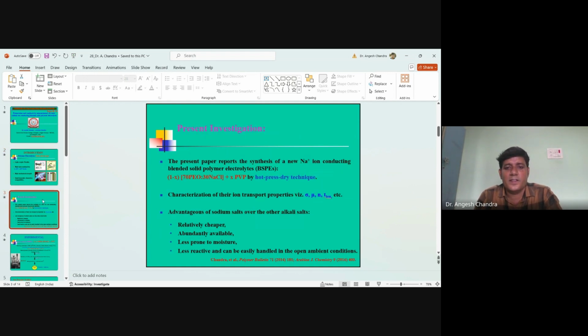Now in the present investigation, we have synthesized new sodium ion conducting blended solid polymer electrolytes, PEO, NaCl and PVP, and characterized their ion transport properties like conductivity sigma, ionic mobility mu, mobile ion concentration n, and ionic transference number t_ion. The advantage of sodium ion salts over other alkali salts is that they are relatively cheaper, abundantly available, less prone to moisture, and less reactive, and can be easily handled in open ambient conditions.